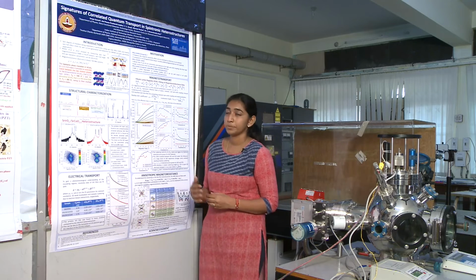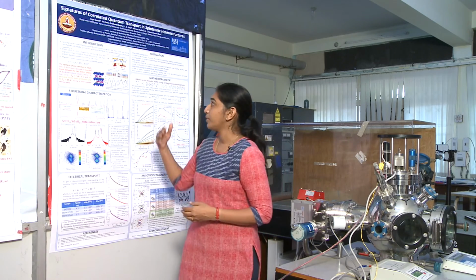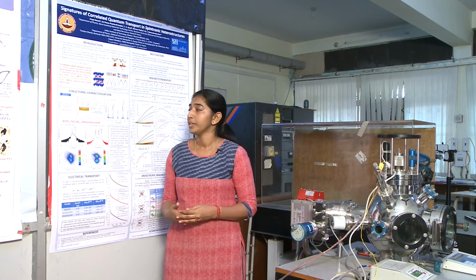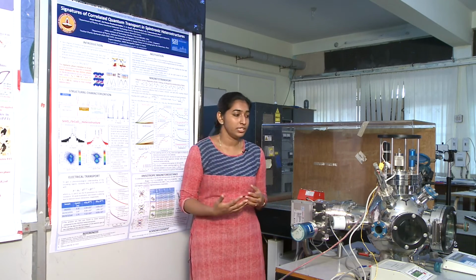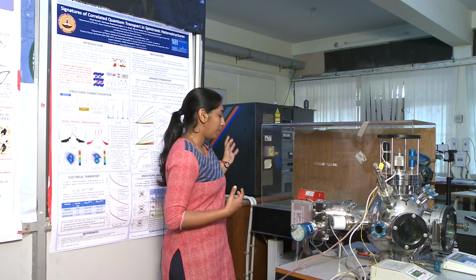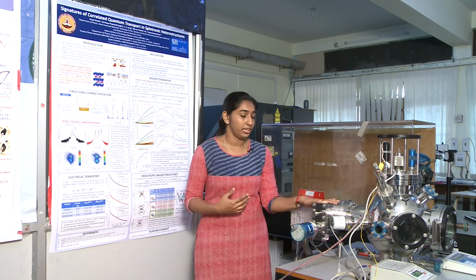Hi all, I am Shreya. We are working on strongly correlated quantum transport in spintronic heterostructures in collaboration with University of Montpellier from France. So here we are studying the spin transport using SrIrO3 as the metallic layer, which has high spin-orbit coupling, and SrCoO2.5 as the magnetic layer. So here we have optimized the deposition parameters for the bilayer system using the pulsed laser deposition setup we have in our lab,